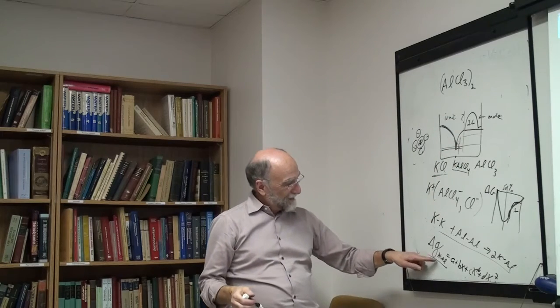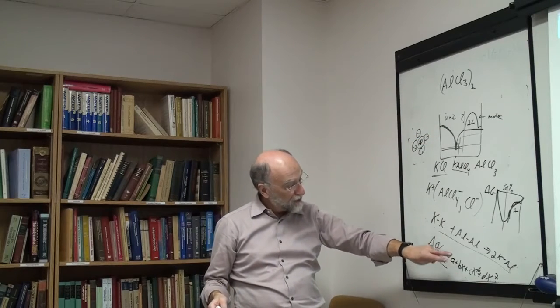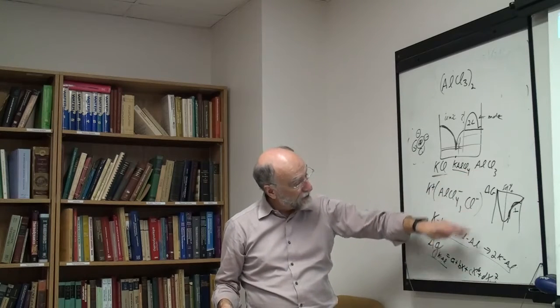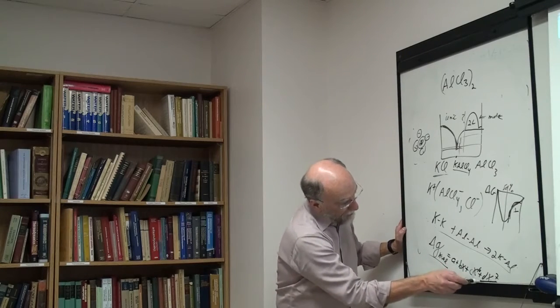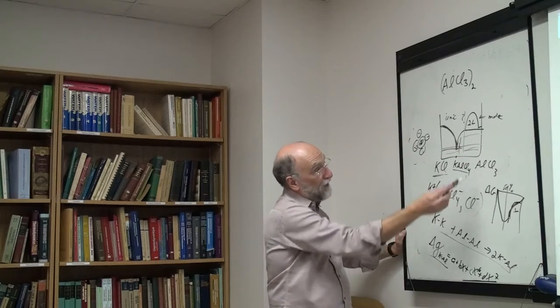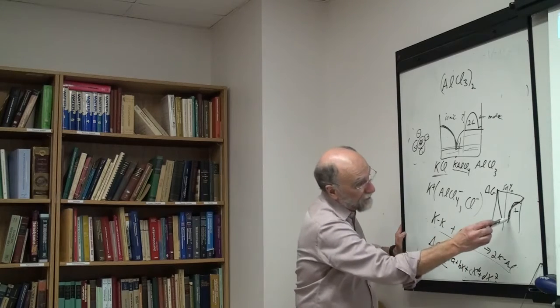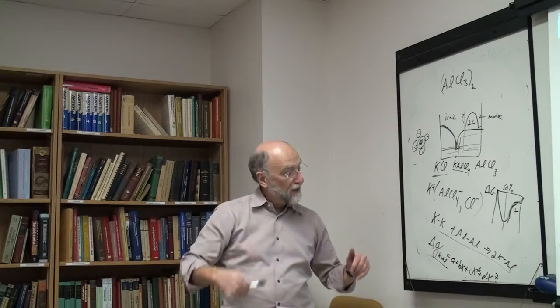Can you read that? In order to fit the Gibbs energy curve to do the optimization, we have delta G as A plus Bx plus Cx squared, whatever. Then we have a couple of powers which are quite high. X is x of AlCl3 to the 6th plus x to the 7th. We use high powers so that these terms only have some effect over on this side where x gets close to 1. If you're over on this side where the mole fraction of aluminum chloride is small, then these terms are very small and have very little effect. These terms are positive, and they give you the flip in here. We usually have two terms, one positive and one negative, because they have to kind of counterbalance each other. That's how we like to do it.